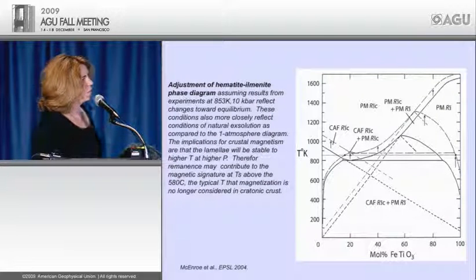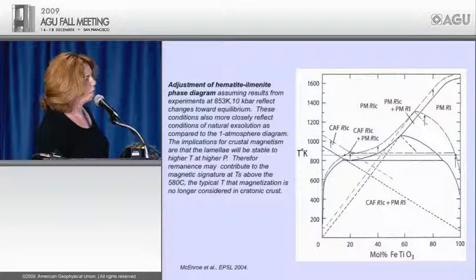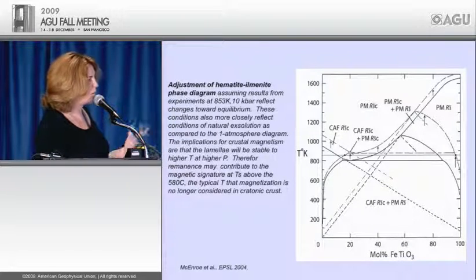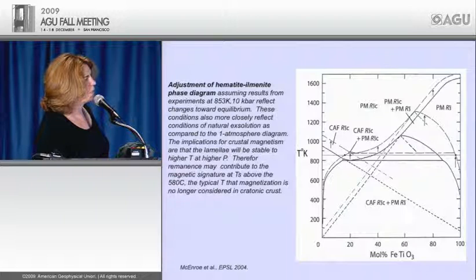Now, what this led us to think about was the fact that if these lamellae aren't being reabsorbed, what's happening to the solid solution at depth? And what we came up with is that the solvus itself appears to have an effective pressure on it. Simon Redford and Richard Harrison looked at neutrons at pressure in this region in the iron and iron-titanium compositions here. And what they found is the ordering increased with pressure. And based on that observation, along with our observation that the lamellae were not being reabsorbed, but that they were stable, we felt that there probably was a stability to the solvus at depth in the crust.